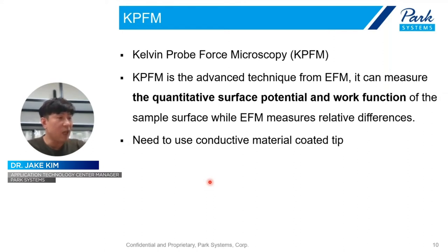And here's the KPFM, the Kelvin probe force microscope, but this KPFM is the advanced technique from EFM. It can measure the quantitative surface potential and work function of the sample surface, while EFM measured relative difference. Of course, it is electrical measurement, so it requires a conductive material coated tip.